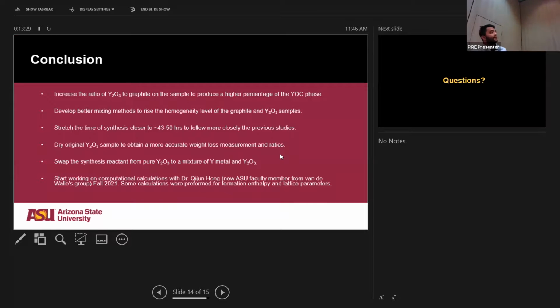So in conclusion, what we need to do is to increase the ratio of yttria to graphite in the sample or the procedure, so that we can get a higher percentage of the yttrium carbide phase. Develop better mixing methods to raise the homogeneity level of the graphite to yttria samples. Again, I did mortar, so it's just 10 minutes of giving a good mix, and I thought it was okay, but I think it's going to have to be further studied. Stretch the time of synthesis closer to 50 hours to follow more closely the previous studies. Again, I only ran for 16 hours, and I'm sure that is not enough time for it to actually react.